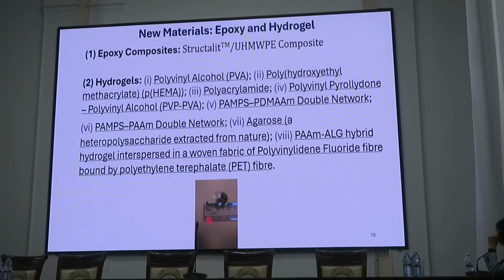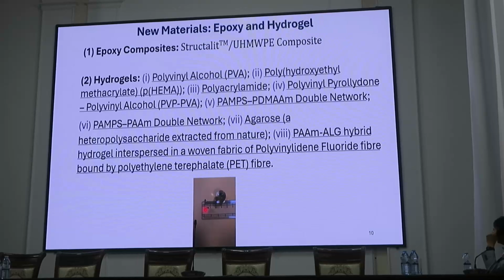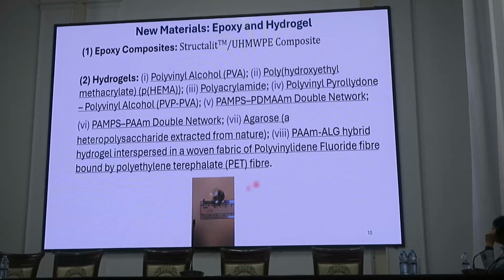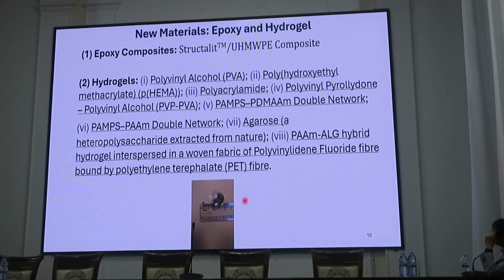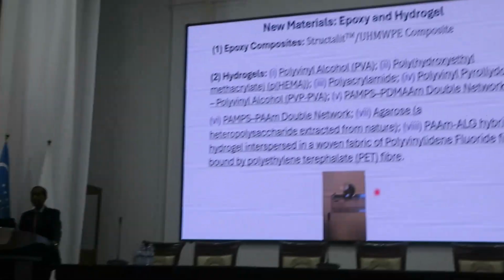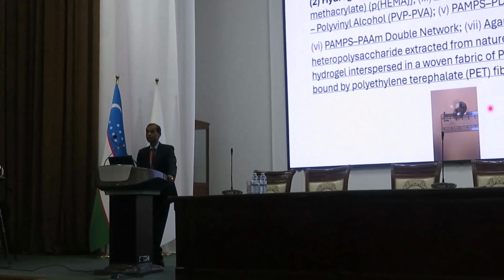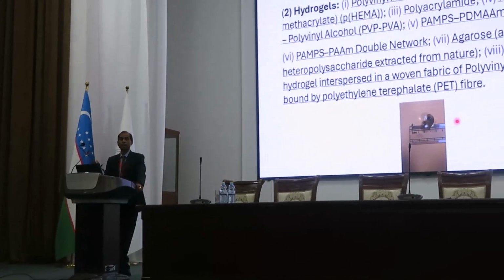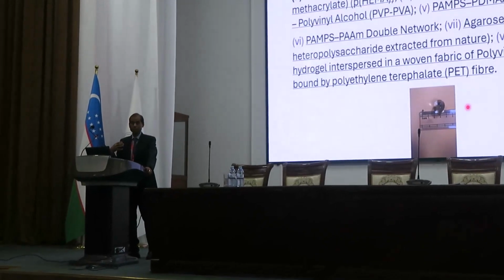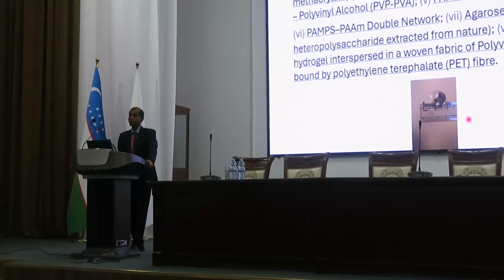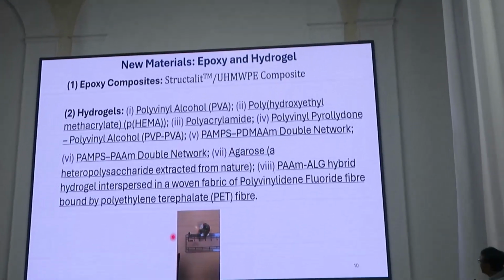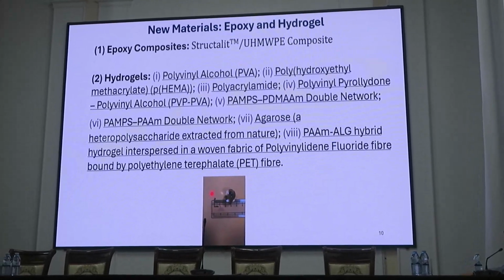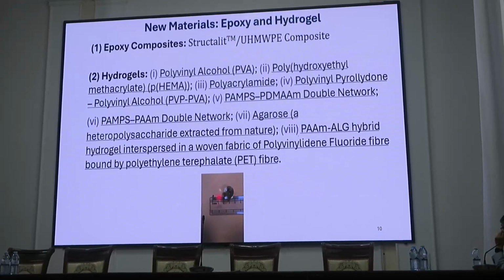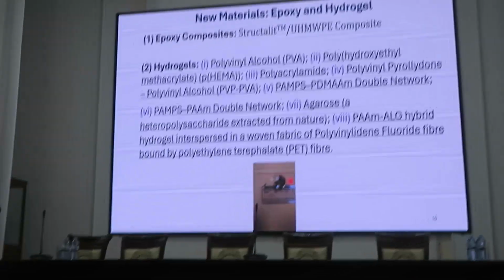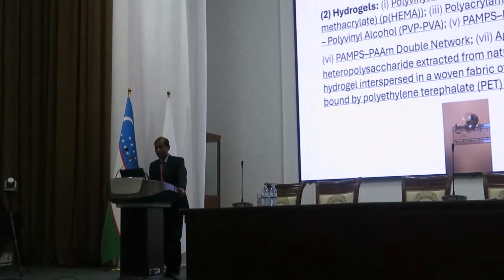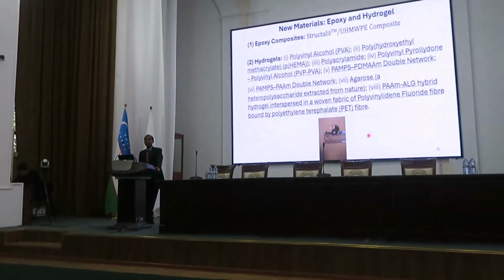Hydrogel is basically a polymer which absorbs a lot of water molecules. For example, if you have tried bubble tea, the bubble inside the bubble tea is actually hydrogel, but this is a natural hydrogel. The natural hydrogel is very good in terms of biocompatibility with us, but in terms of mechanical and tribological properties, they are not good. Therefore, we have to go for synthetic. This group compares one small particle of hydrogel, which is dry, and after soaking in water, it expands so much. Almost 80% water by volume you can have in the hydrogel. So obviously, water is used for lubrication.